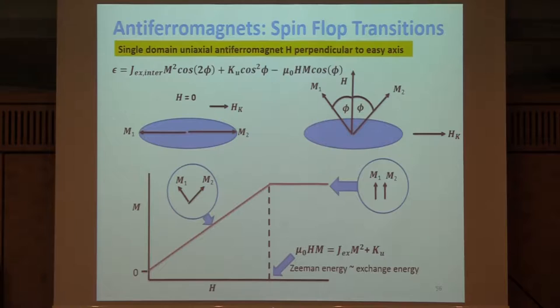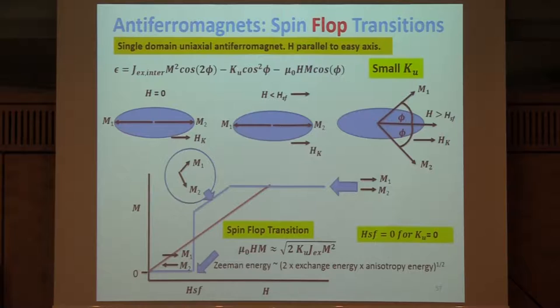But the other behavior that Ham told us about was the spin flop behavior. So now if I apply the magnetic field along the easy axis, initially as I increase the field, nothing happens. Here's the blue. And so I get to a critical field. So just from this expression for the energy, if you just minimize that, then you can easily find out where this transition is occurring. And it's occurring where the Zeeman energy is about the square root of twice the exchange energy times the anisotropy energy. And then it goes from the...